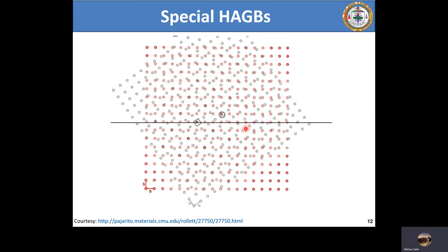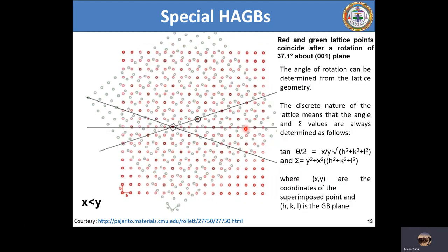Now as we see, after a certain number of rotations, here it is around 10, by a certain angle which is equal to 37.1 degrees about the 001 plane, the lattice plane which was here has completely been brought into coincidence with this lattice point here, and similarly the lattice point here remains unchanged. So what we can say is that,